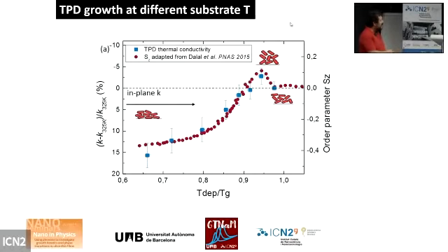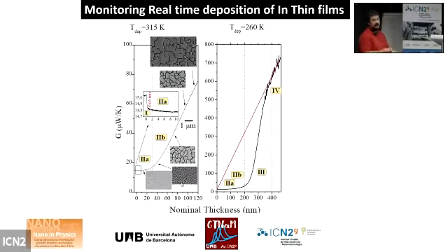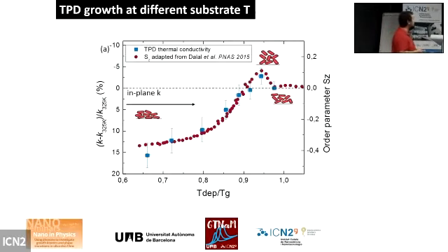It means, this is the ratio, the reduction of the thermal conductance compared to the bulk, that we have around 50% of reduction, and we were able to measure up to here and to follow that. Of course, thermal conductance and the order of the molecules in the substrate do have a relation. This is not the thing that we have been studying with that method, because we have been trying essentially to check that initial depression of the thermal conductance.